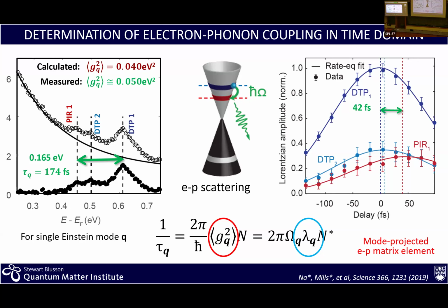And just experimentally, here you're looking at a very weak signal. These signals are about 4 orders of magnitude weaker than what you have at the chemical potential. So we are doing photoemission not from the occupied part. We are promoting electrons above. They have a limited lifetime, 50 femtoseconds for electron scattering and 170 for electron-phonon scattering. So the lifetime is really very short up here. Still you can see that because you're working on a reasonably flat background and you have very high signal to noise. But yes, resolutions are your limit.